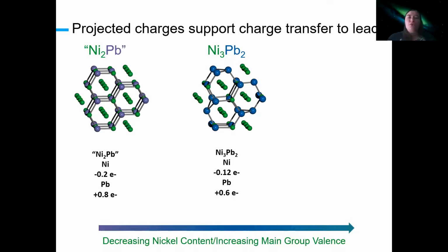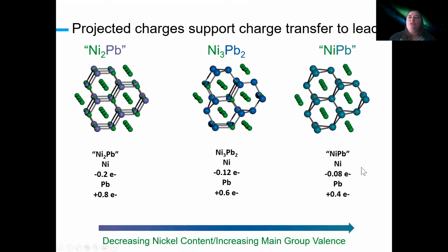And then in order to do an apples to apples comparison, we created the theoretical 2-to-1 nickel lead structure, and noticed that there is more significant transfer from the nickel to the lead than in the theoretical 1-to-1 structure. And this suggests that there is something fundamentally going on here, and that even though these are not ionic compounds, our chemical intuition for a more significant charge transfer when you have a lower main group valence, meaning you need more electron density from the nickel in order to complete your valence electron count, is that we're seeing that trend across the series. So that was particularly exciting to me.